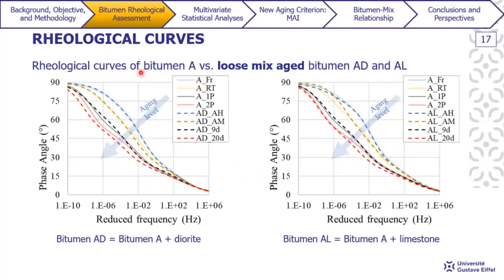Well, now I'm going to compare the four aging states of bitumen A versus loose mix aged bitumen AD and AL. Bitumen AD is a bitumen that was recovered from a mixture composed of bitumen A plus diorite aggregates, whereas bitumen AL was bitumen A plus limestone. Here I use just four aging levels that are represented by these dashed lines. The blue one represents the bitumen that was heated minutes before mixing. The brown one represents bitumen that was recovered right after mixing. The black one represents the bitumen that was recovered from an asphalt mix that was aged for nine days, and the red one for 20 days.